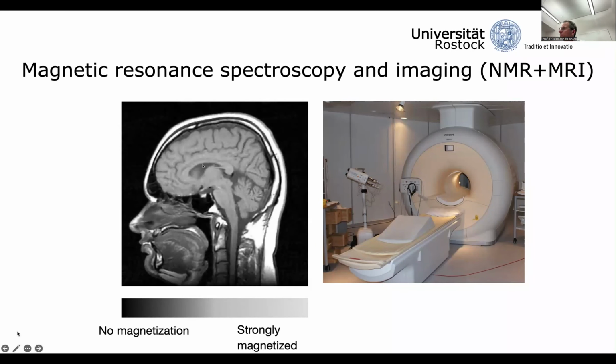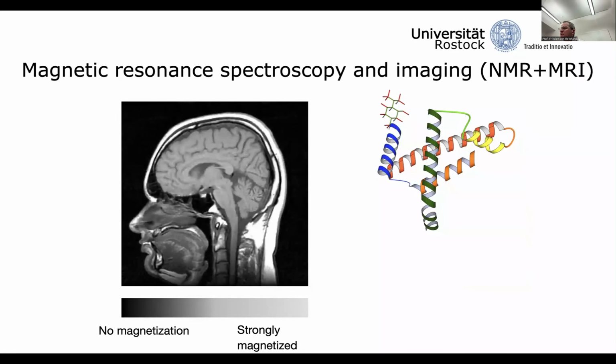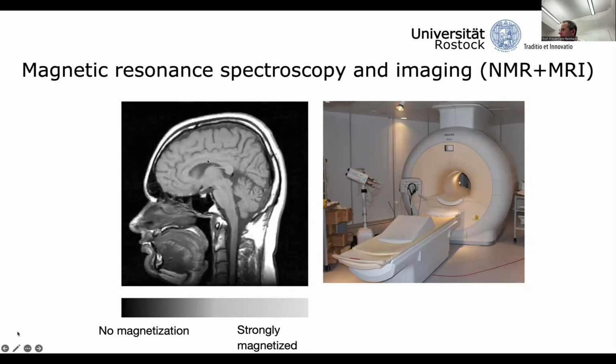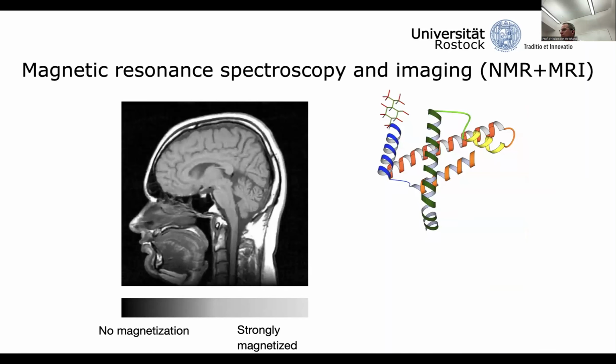It is not possible to resolve details smaller than around a millimeter by traditional induction detection, and this is only a technical limitation. In fact, the signal itself does not scale with the size of the sample. If you could come nanometers close to a polarized section of tissue, the magnetic field that you would feel would be the same as at a millimeter distance of a millimeter-sized tissue. So if we had an atomically small sensor that could come nanometers close to molecules, then NMR spectroscopy could be extended to single molecules and much smaller entities.